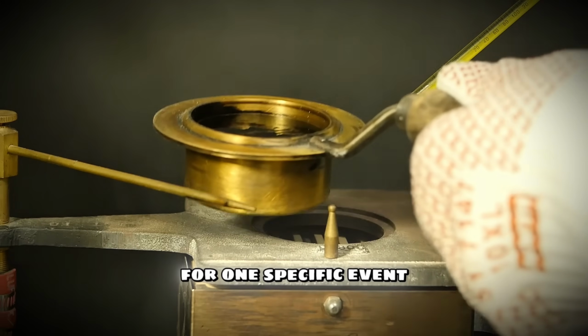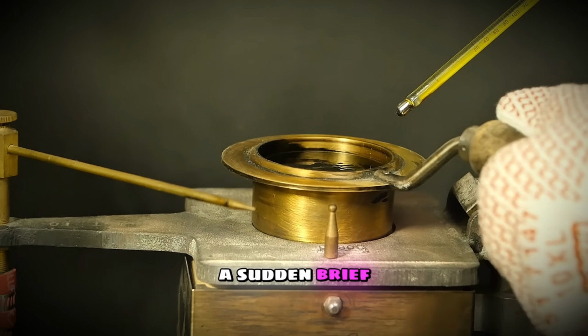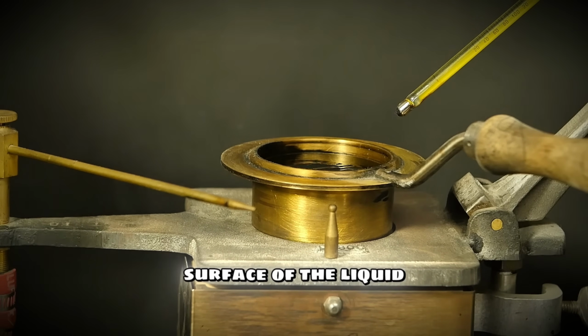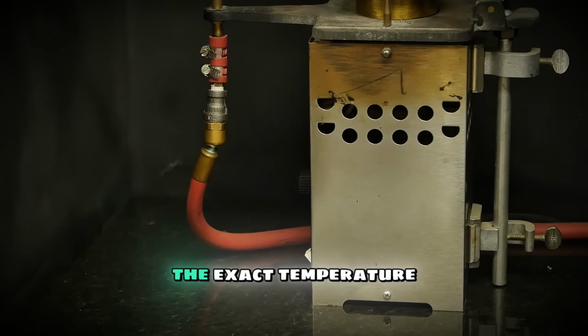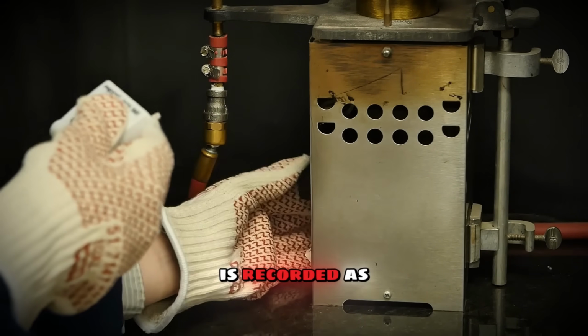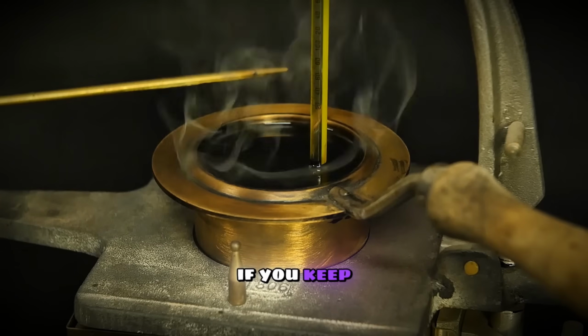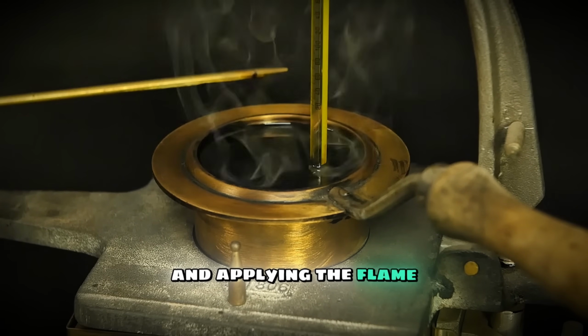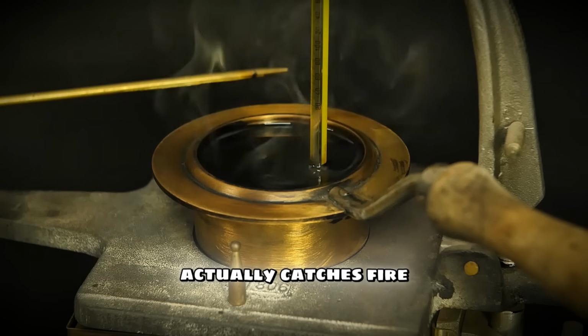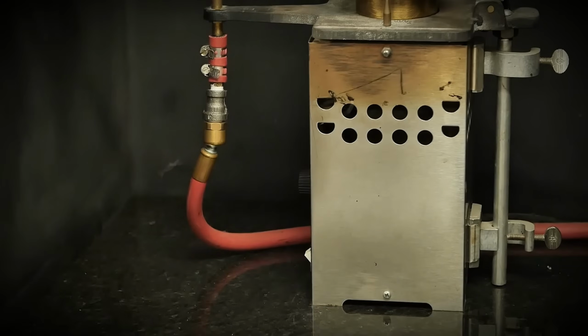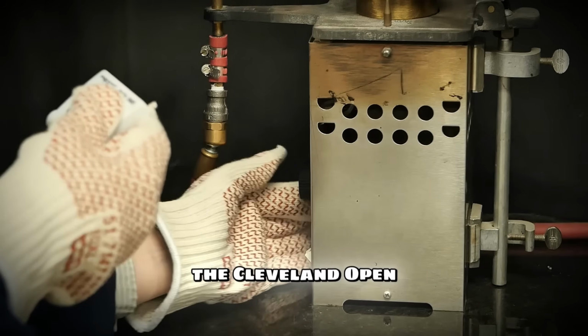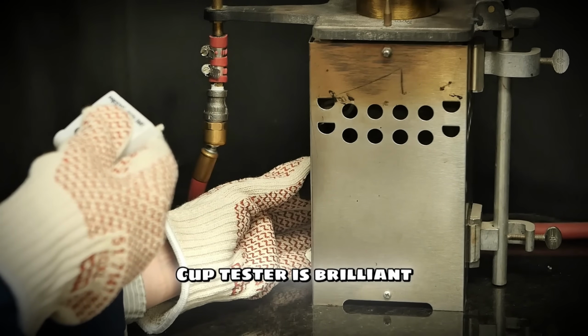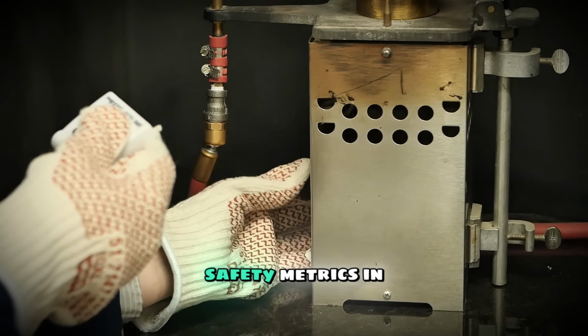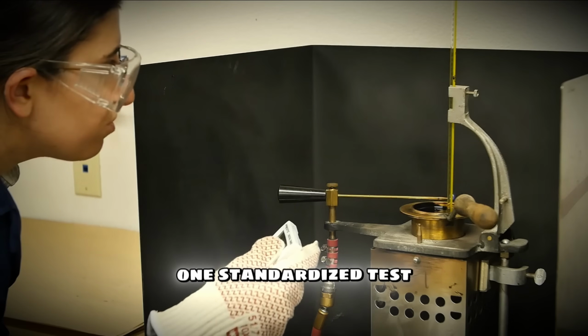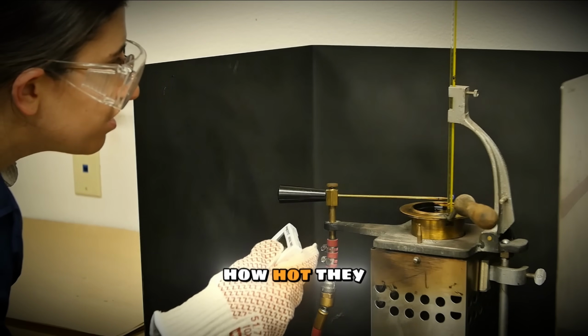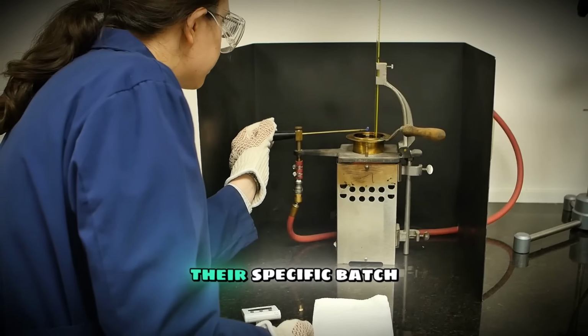They are watching for one specific event, a sudden, brief flash of blue fire across the surface of the liquid. The exact temperature at which that flash occurs is recorded as the flash point. If you keep heating the sample and applying the flame until the asphalt actually catches fire and burns for at least 5 seconds, you have found the fire point. The Cleveland Open Cup Tester is brilliant because it gives you both of these critical safety metrics in one standardized test, telling paving crews exactly how hot they can safely heat their specific batch of asphalt.